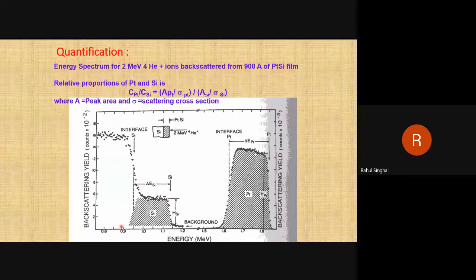It tells you that in your sample you have platinum in more amount compared to silicon. It means the atomic concentration of platinum is larger than silicon, because in case of platinum you are getting more backscattered ions, meaning the yield is more. You can see here on the y-axis, for platinum the maximum yield is around 14 into 10 to the power minus 2, but for silicon it is around 6 only. So if you are able to find out the area of the peak by using some curve fitting, you can easily estimate the elemental concentration present in your sample.